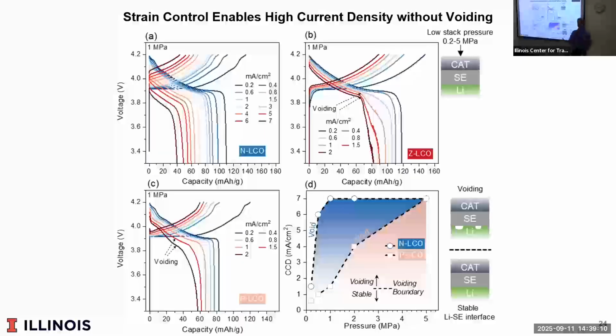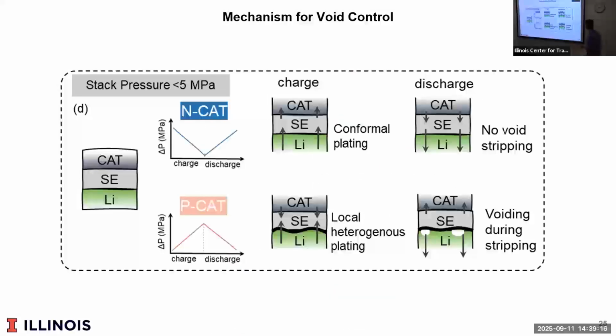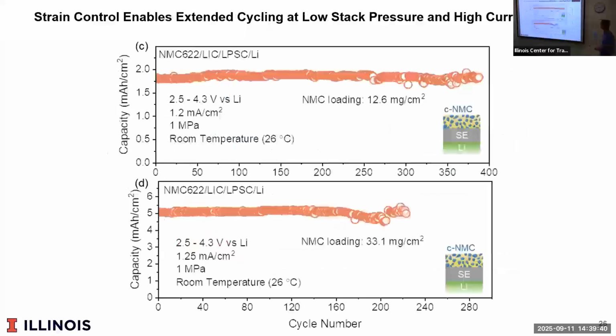So it's basically playing with the internal mechanics of the battery to make it work. And this is, again, the details. We just had the paper accepted. We're happy about that. So if you're really interested, I'll send you a version of it if you want to spend a few hours on material science of batteries. But the short version is that by playing with the mechanics, we can make a solid state battery that is much happier, because we're not pulling on the ceramic layers and causing them to crack. And when we've done it really, really well, this is 400 cycles with basically no capacity fade, which I think is pretty significant.